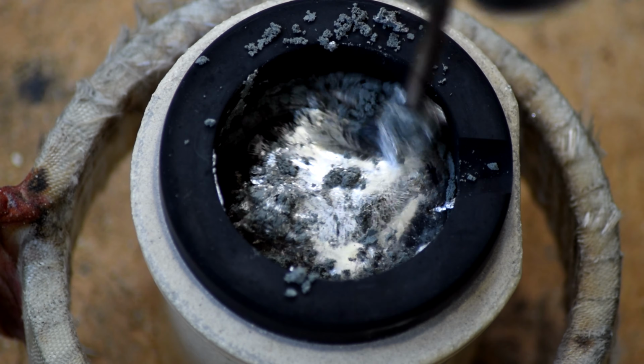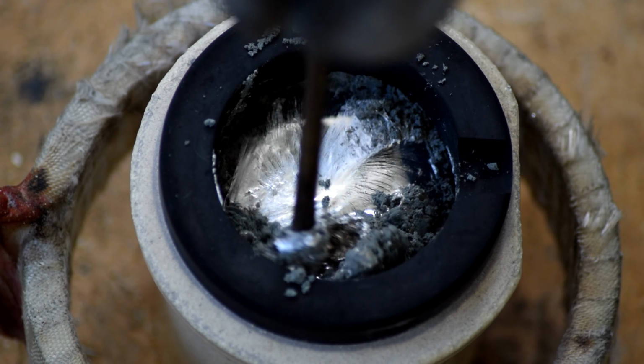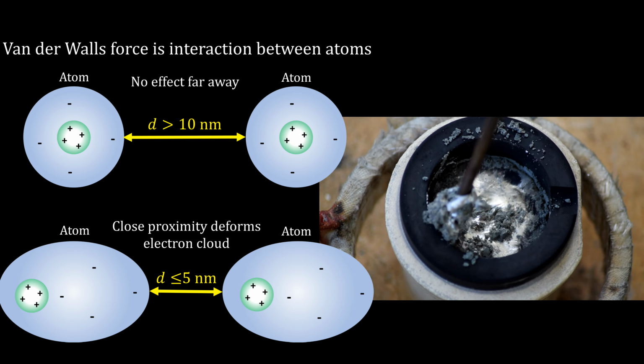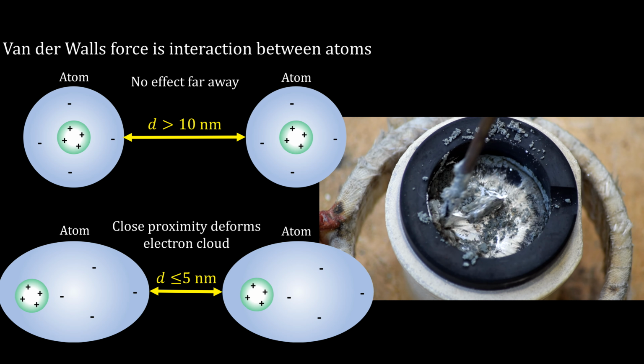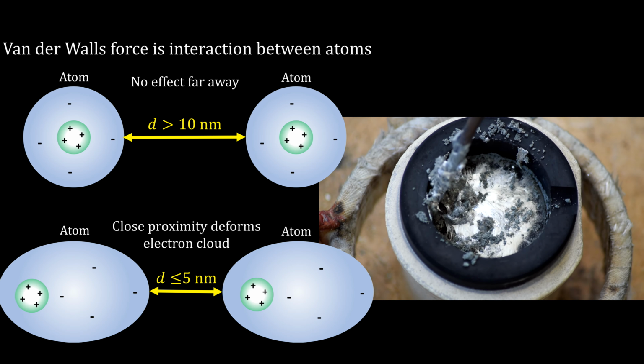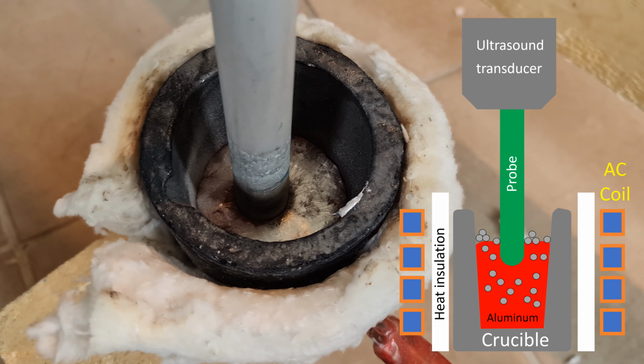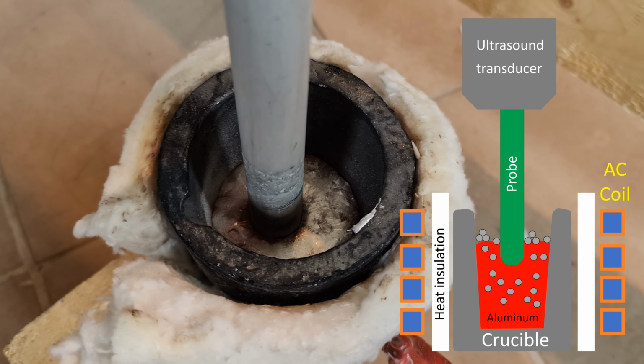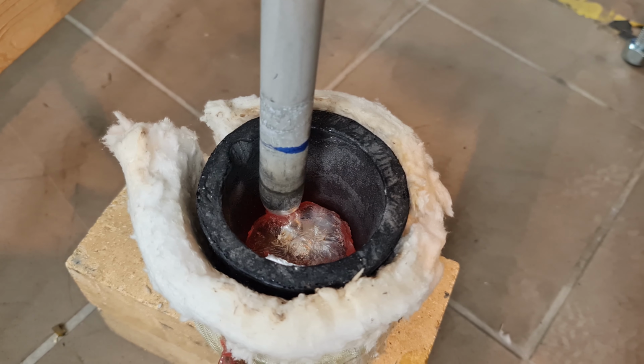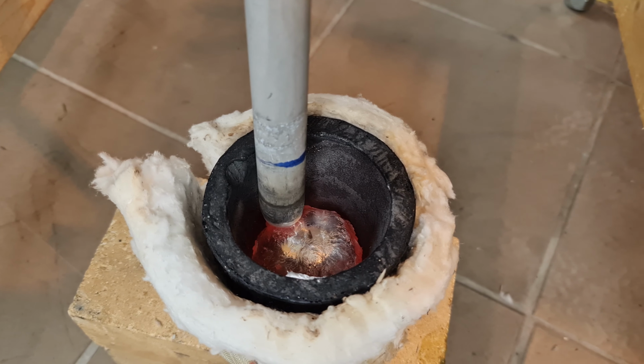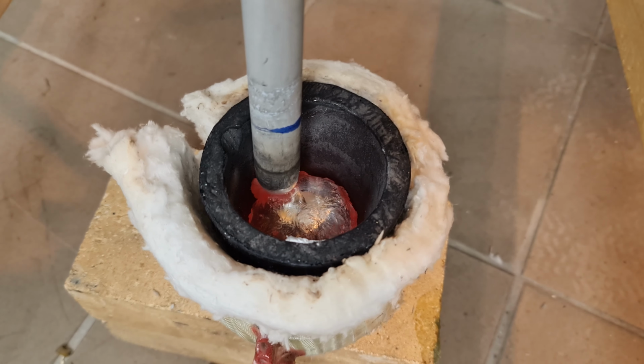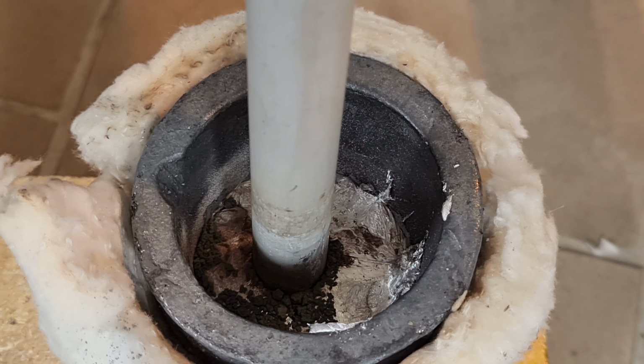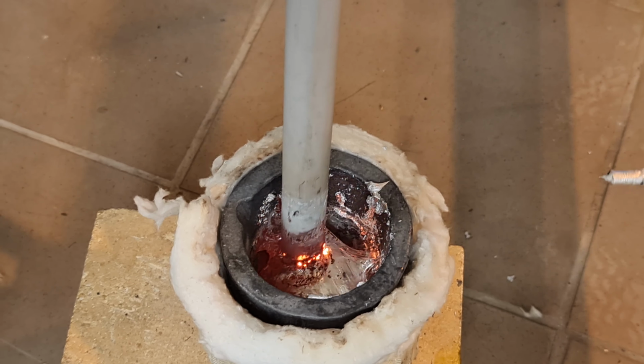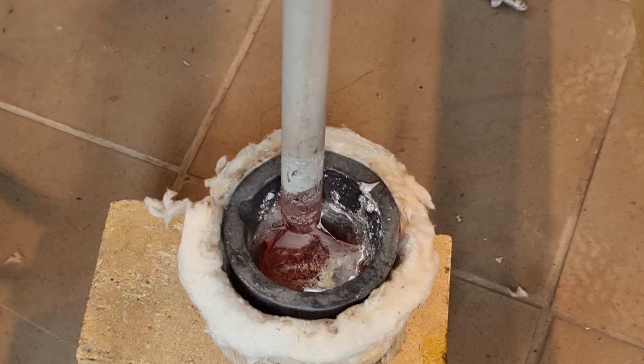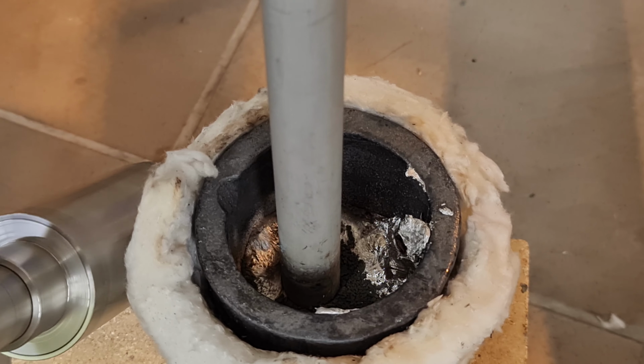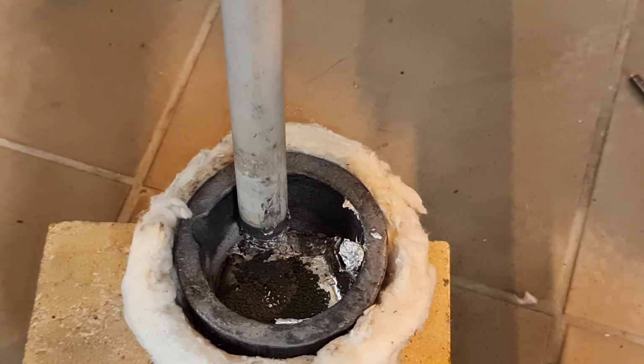Simply pouring them on the surface leaves you with clusters of particles on the surface due to poor particle wettability and van der Waals forces, which hold particles in agglomerates. To solve this challenge in industry, mechanical ultrasound treatment is used. Here, 18 kHz waves jiggle the metal, which helps remove dissolved gases in molten metal and also aids in nanoparticle dispersion in it. Visually, nothing interesting happens, but the process creates a unique and unpleasant screeching sound. Take a listen.